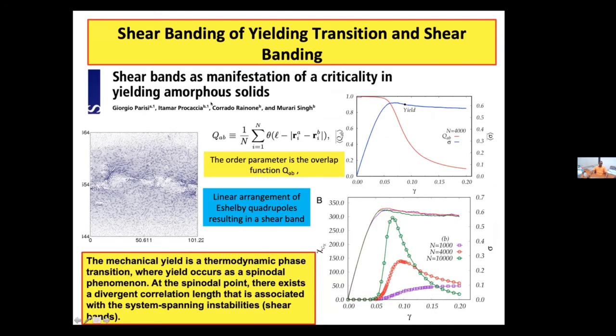And in that context, Giorgio, Itamar, Corrado and Murari looked at this yielding process using replica calculations. If you take two configurations, call them replicas, and they start from very similar structures, they have a similar overlap, where the overlap Q, the order parameter, is close to 1. Then you shear them and look at how the overlap decays. And it seems that this overlap, Q average, actually shows a very sharp decay at the yielding point.